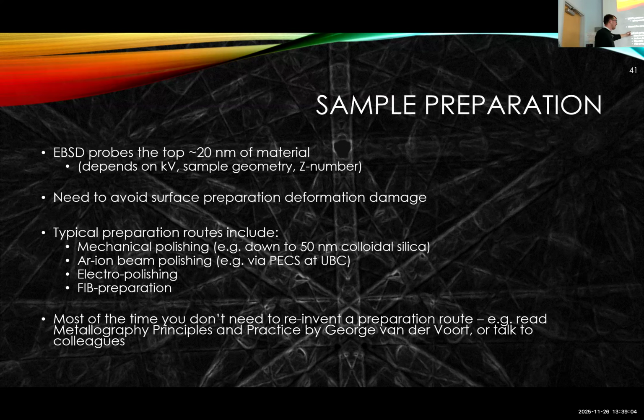We have many mechanical polishing wheels. Typically, we polish with a final finish of 20 nanometer colloidal silica or 50 nanometer colloidal silica. We also have an argon broad ion beam polisher in this building called the PECS system. It's a very gentle surface sort of tickling of the surface. We also use electropolishing. We have a controlled electropolishing system over in 419 in Frank Forward. And we can also use FIB preparation, as I've shown you in this case.